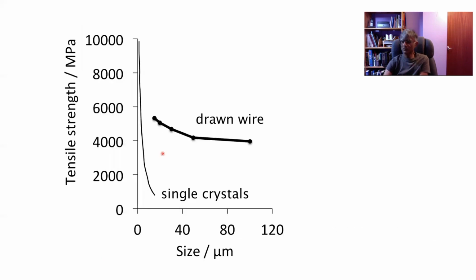I won't go into the problem just yet, but if I compare this wire against the single crystal where the strength drops dramatically, this is insensitive to size simply because it acquires its strength not through perfection, but by having lots and lots of dislocations inside the material.